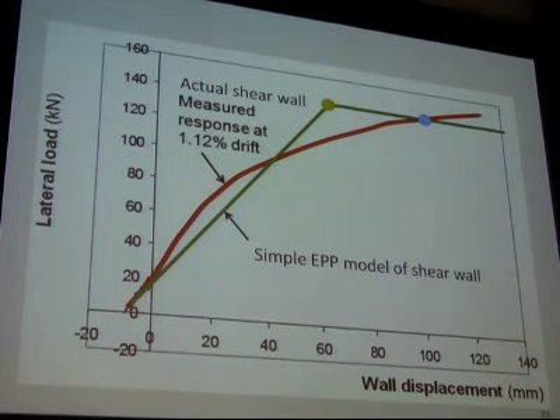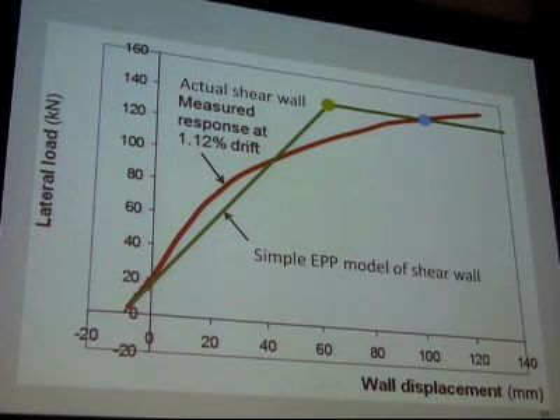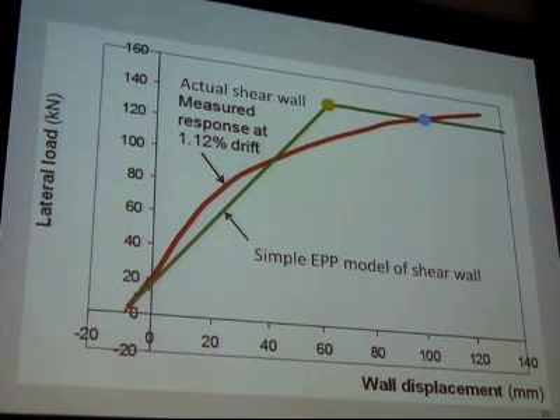Well, we've done a lot of work on this, and one of the issues has to do with how you model the shear walls. This is a theme through a lot of what I'm going to talk about in the next little while: a lot of people have used a simple elastic plastic model. That green line there is an elastic plastic model of a shear wall, using the reduced effective rigidity as your slope, and you end up with a yield point, which is the yellow dot. But real shear walls have a line that's more like the red one. It's actually a curve, closer to a trilinear response, where you have an initial uncracked response, and then you have a cracked portion of the response. And the yield curvatures then become much larger.